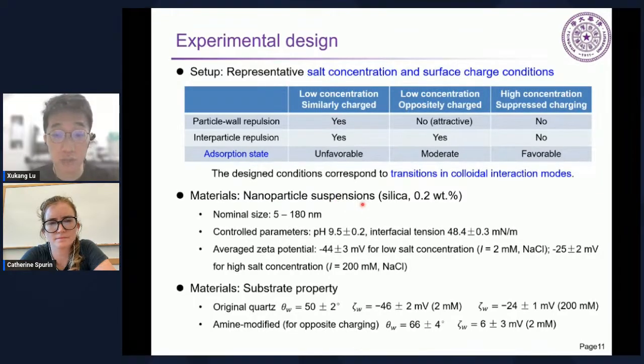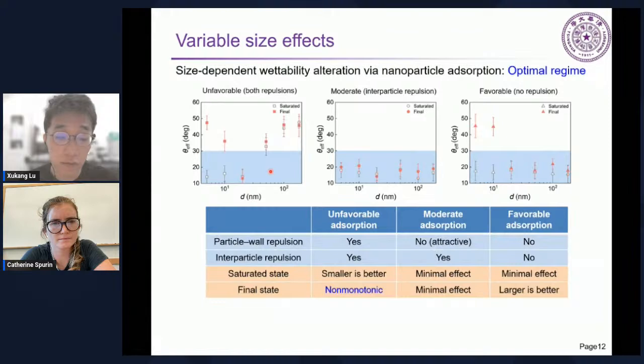For nanoparticle suspensions, we fix all the other parameters, control them, and just vary the particle size over a wide range. Zeta potential may change corresponding to physicochemical conditions, and the surface may also be modified under different conditions. Then we look at the summary of the results. If we plot the apparent wettability versus the particle size under different adsorption conditions, you will see many different size effects. It is variable, relevant to the treatment condition and also the adsorption condition. Sometimes it's non-monotonic, sometimes smaller particles perform better, sometimes it's a minimal effect, and sometimes larger is better.